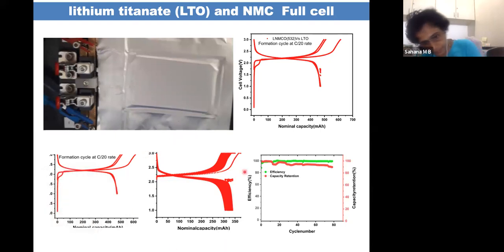This graph over here, you can see that when we move from this point to this point, the number of cycles is increasing. That is, we are charging and discharging n number of times. Now if you see this graph, the x-axis gives you the cycle number and the y-axis gives the efficiency. That is, if the first cycle capacity is taken as 100, after 80 cycles the capacity becomes only 80, or in this case around 75.